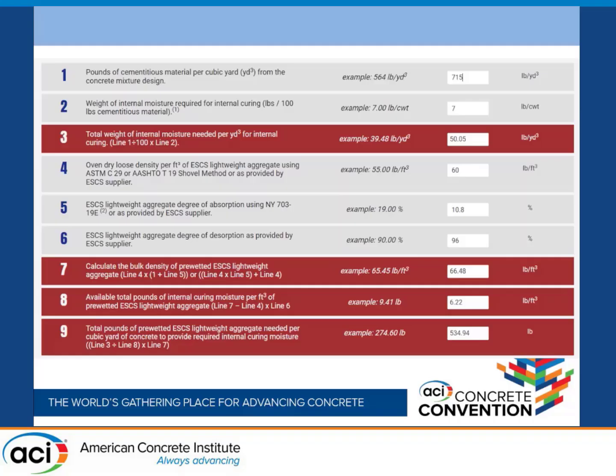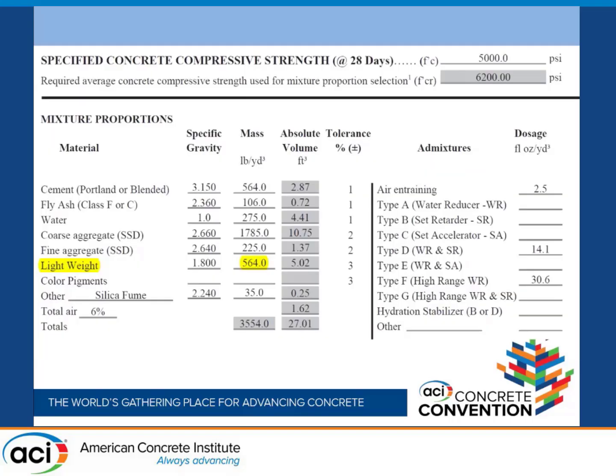I pulled that equation up, based on the information that Mike Dallaire had at the time, and plugged in the absorption and desorption numbers from work that the guys at Purdue had done, and I told Mike that he needed to put in at least 535 pounds of our material, which has a lower absorption than some of the other materials. So you'll see internal curing projects with significantly less than this, but this was because of our specific material. So he would have to put in at least 535 pounds to provide enough internal curing.